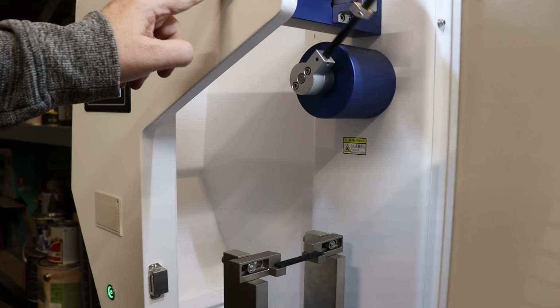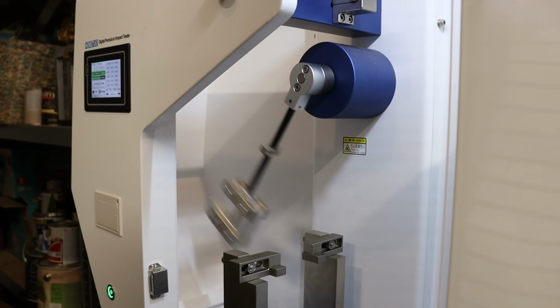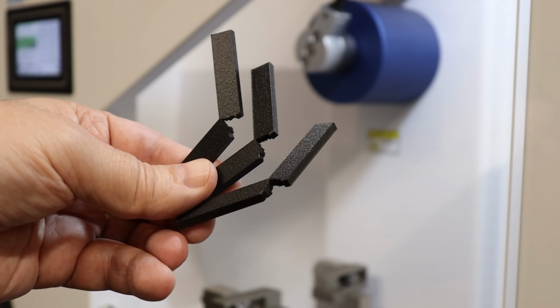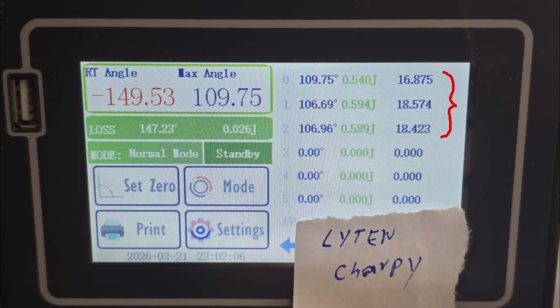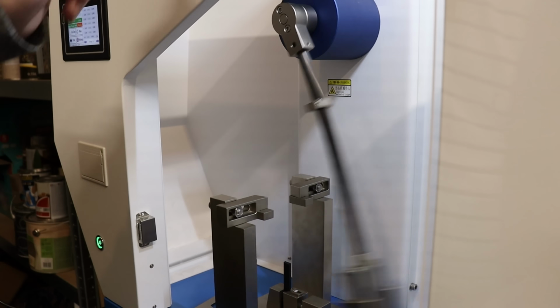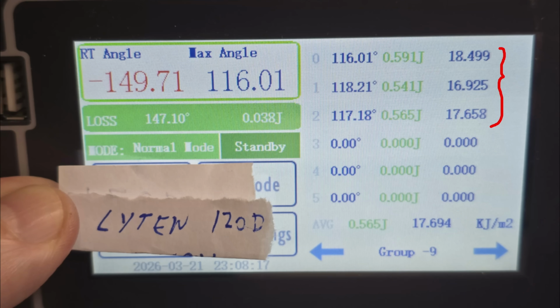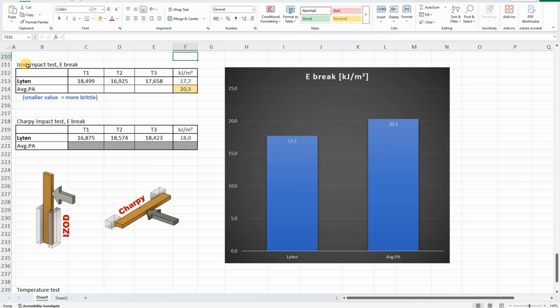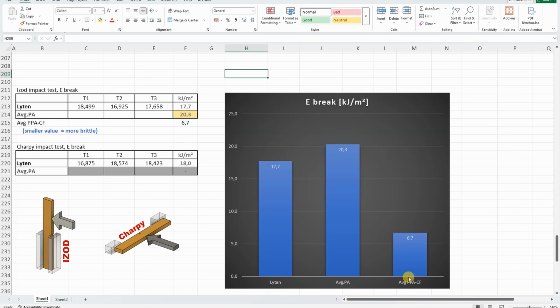Impact test. I started with the Charpy standard, and similar break in all 3 cases, and the result in right upper corner. And now this is the Izod standard. And complete break was only when the hammer swung back. And again the result in right upper corner. Result for the Izod and for the Charpy impact testing, and for the Izod I have a comparison average PA. And usually fiber reinforced materials are very brittle, but not nylons. Well, this Lyten is a little bit weaker compared to the average PA, but this is very good value too. And I check in the meantime, much better compared to the average PPA CF.